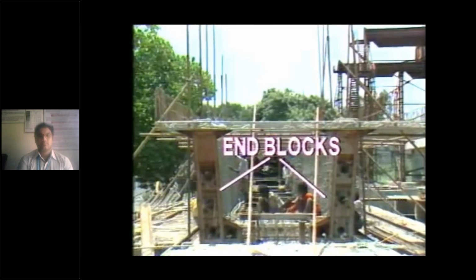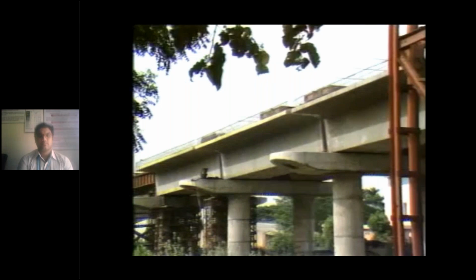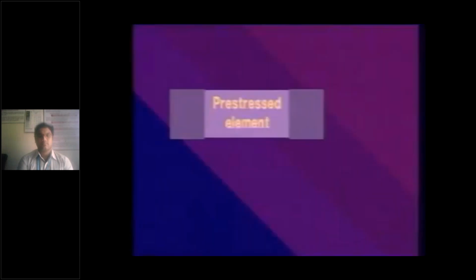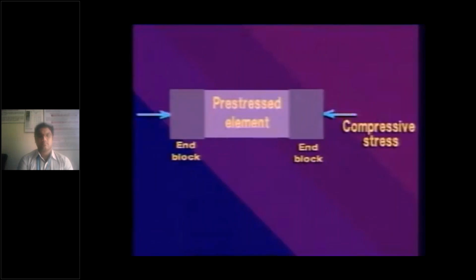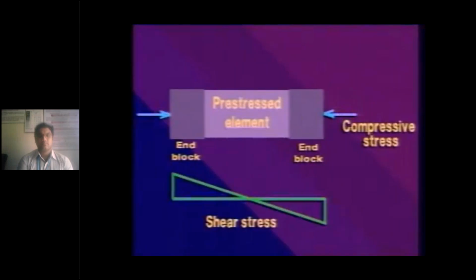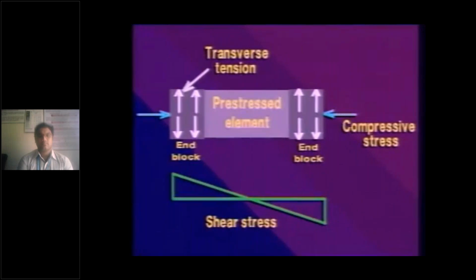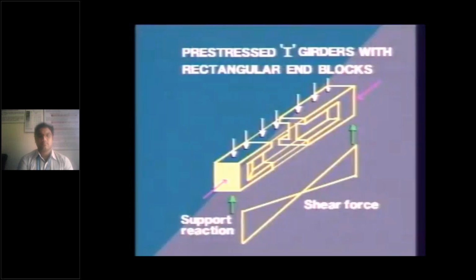Pre-stress in the concrete changes from concentrations at the anchorages to the calculated stress distribution so that it is subject to high stresses. The end block is subjected to high compressive and shear stresses with transverse tension. Adequate shear and spiral reinforcements are to be provided at the end block as per design. Even in the case of flanged beams, end blocks are made solid and usually rectangular to provide the necessary bearing area and to prevent excessive stress concentration.